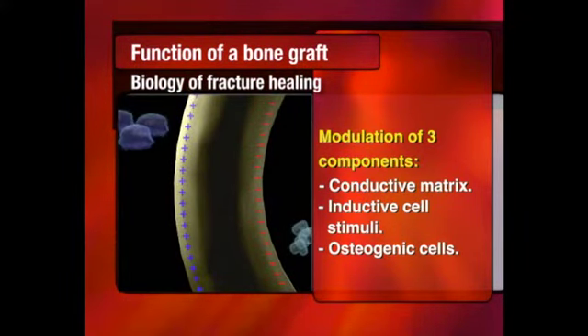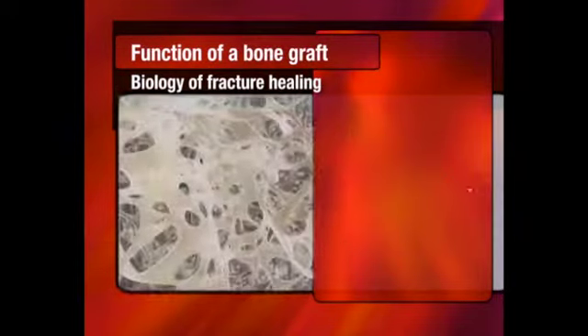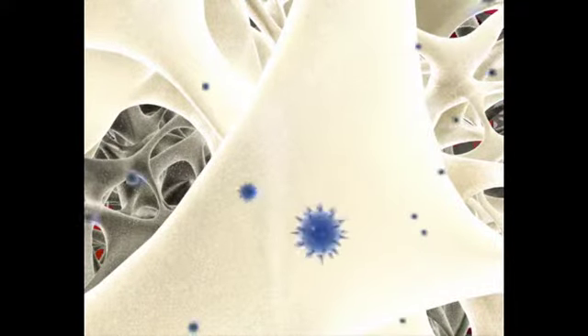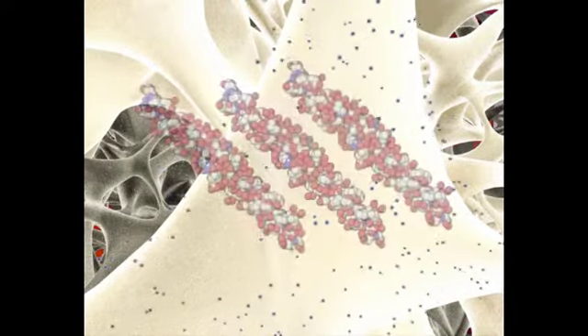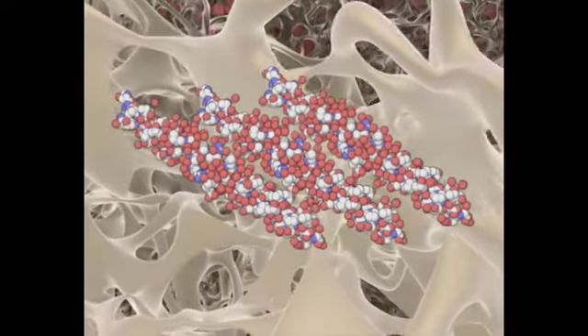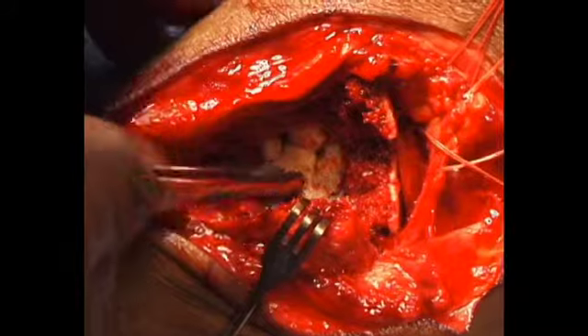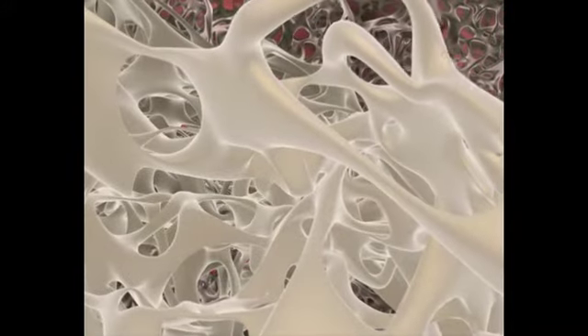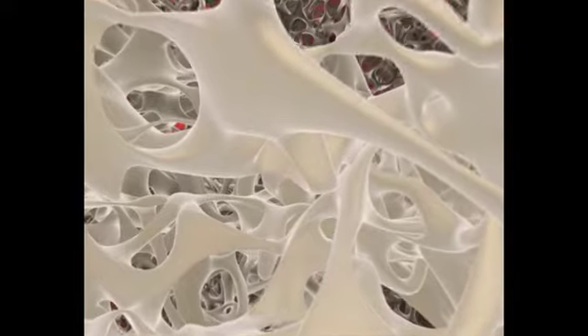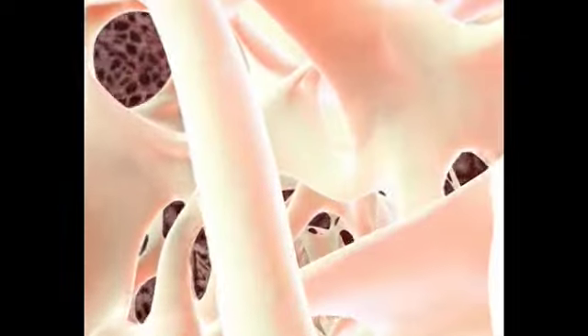The fracture healing cascade involves modulation of three components: a conductive matrix, inductive biologic cell stimuli, and osteogenic cells. At the time of fracture, there is an immediate binding of multiple plasma proteins to the matrix present at the fracture site. This matrix may be anything from the fibrin clots that keep both ends together to a bone graft material implanted by a surgeon. This matrix is crucial to new bone formation and must present a substrate with specific surface kinetics and three-dimensional architecture to facilitate the attachment of migrating pluripotential mesenchymal stem cells. Matrices that fulfill these requirements are called osteoconductive.